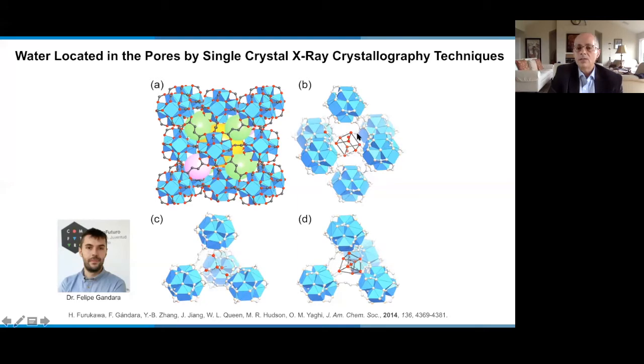This is another pore that makes cubic seeds. And depending on how much water you use, you can have the tetrahedral seeds or these cubic seeds. Beyond these seeds, the new water molecules come in and they bind to these waters and not the framework. And so what I'm trying to say is that the reason we have this nice sharp isotherm is that seeds of water go in, they bind strongly to the metal oxide units, onto which you have water molecules that are then attracted from the atmosphere, and that's how the structure builds up. Let's say ice in its pores, or crystal structure of water in its pores.